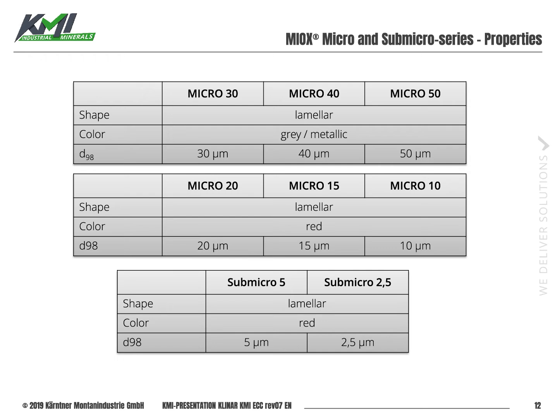So what we do for the gray grades is we grind the products and we classify the ultrafines out as a last processing step to come back to the gray color. This is possible down to the Micro 30, which is the finest gray one, but doesn't make sense from an economical point of view for the finer grades. So there we leave the reddish fine particles in, and the product turns more and more into red.